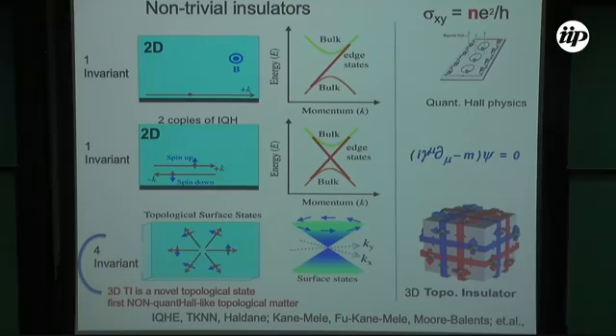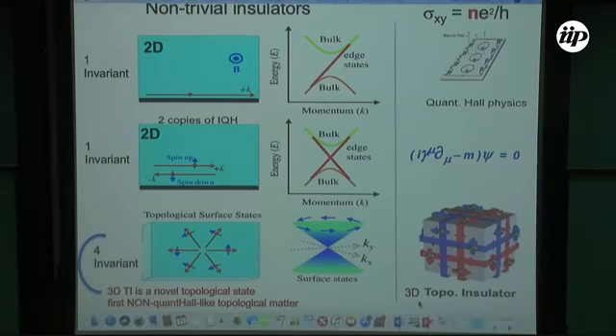So one can hypothetically think, is it possible that we have counter-propagating edge states? Here, this chirality is defined by the fact that you have a magnetic field that defines the handedness of the system. This is why it's chiral. Now one could ask, is it possible to have counter-propagating edge states? That means you have field up, and then edge states in one direction, and then field down, edge states in the other direction. But in that case, your net Hall conductivity, the charge Hall conductivity, is 0, right?